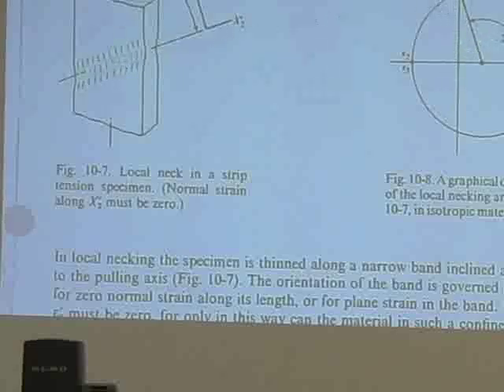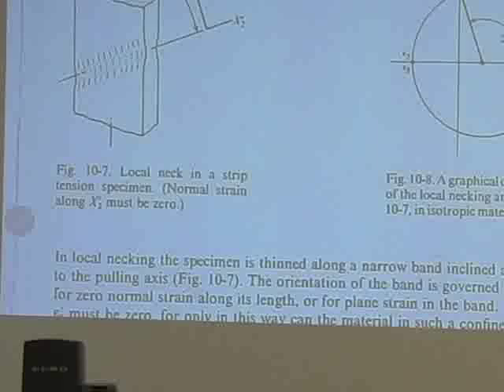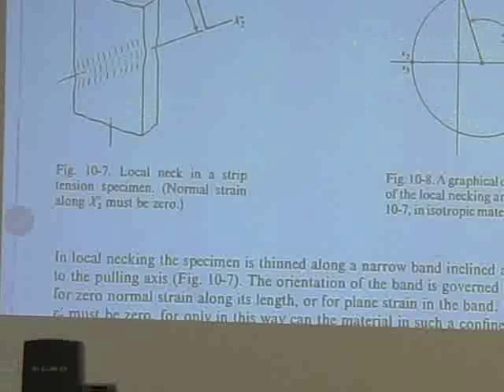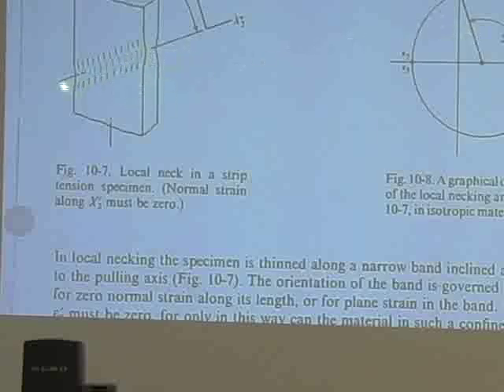A plane strain condition is where one of your strains is 0, so epsilon ij, which is either epsilon 2 or epsilon, it's either where your shear strains go to 0, epsilon 1,2 goes to 0. If this is a unit strain, and this is 0.33 times that unit strain, it turns out the plane strain condition will be at an angle of 55 degrees, because this is 2 theta. We haven't gone over more Mohr circle constructions, so I apologize, but anyway, if you do the Mohr circle on all this, which is the way people used to analyze stresses and strains 70 years ago, you can prove that the angle of these Lüders bands or stretcher strains to the tensile pulling direction should be at 55 degrees.